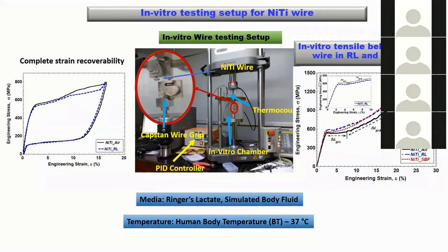Fine. Now, moving on to the complete stress-strain diagram in the presence of just air, the ambient condition, as well as in the presence of Ringer's lactate or SBF, we have seen that more or less it has shown almost similar behavior. It has shown pseudoelasticity also, and it has shown similar ultimate tensile strength and total elongation and so on. So not much influence of the corrosive atmosphere or the body temperature has been seen.